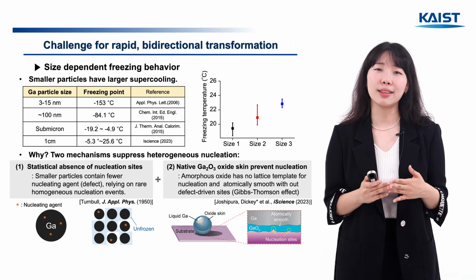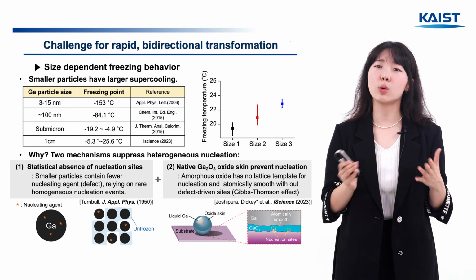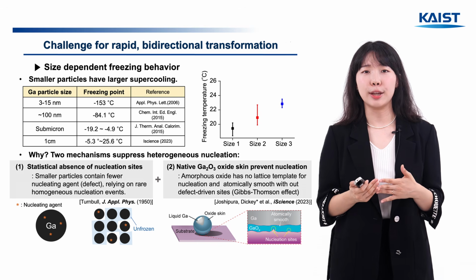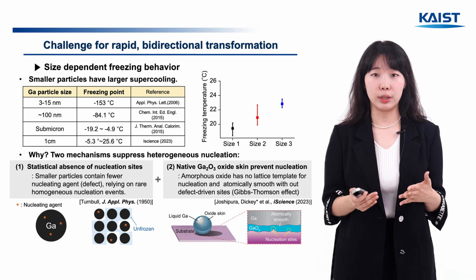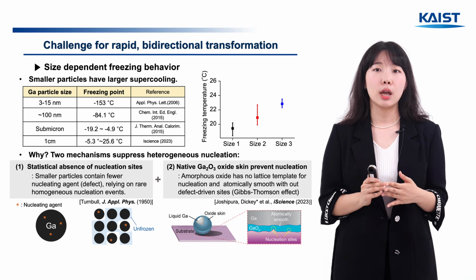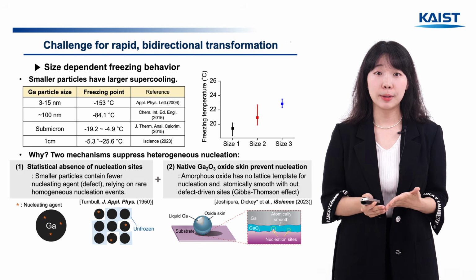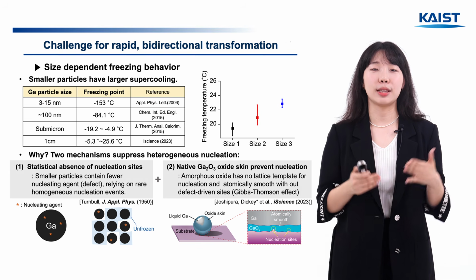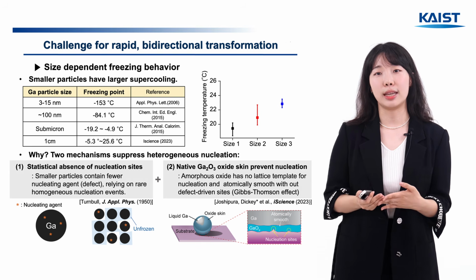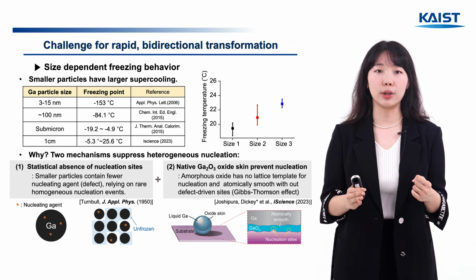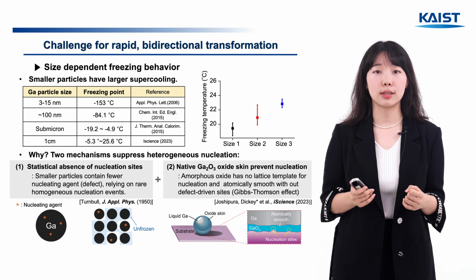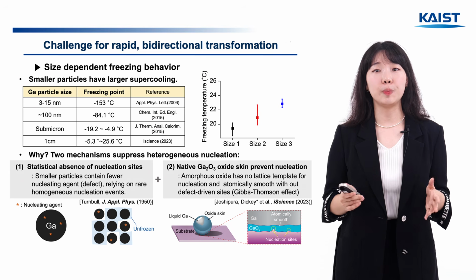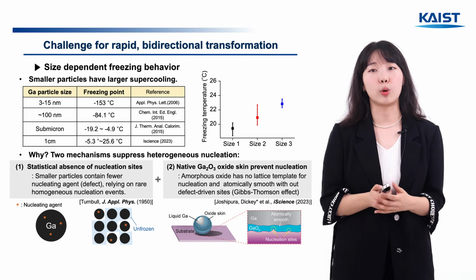And now you might think that smaller particles have more oxide, so the oxide layer could act as a starting point for nucleation. But the surrounding oxide is amorphous, so it cannot serve as a lattice template for freezing to begin. And it also blocks the particle from meeting the external defects. So, the larger the gallium particle, the more easily it freezes.